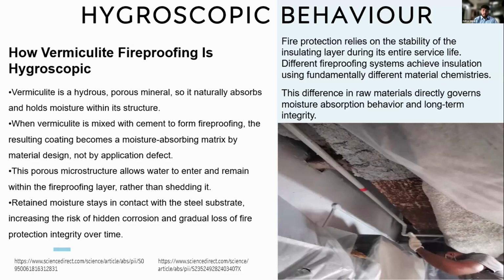Coming on to a very crucial factor, hygroscopic behavior. We have attached two case studies to prove how vermiculite coatings are hygroscopic in nature, meaning they attract water, which is really bad for steel as it will invite corrosion. Vermiculite is a hydrous porous mineral, so it naturally absorbs water and holds moisture within its structure. When vermiculite is mixed with cement to form fireproofing, the resulting coating becomes a moisture-absorbing matrix by material design, not by application defect. This porous microstructure allows water to enter and remain within the fireproofing layer rather than shedding it. Retained moisture stays in contact with the steel, increasing the risk of hidden corrosion and gradual loss of fire protection integrity over time.